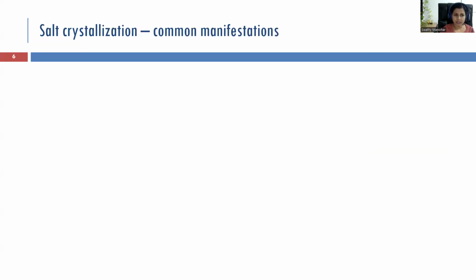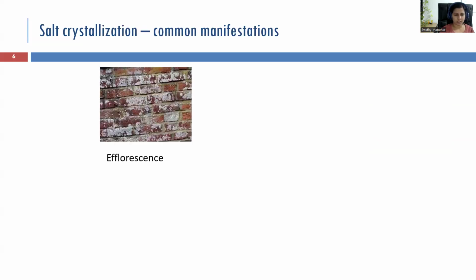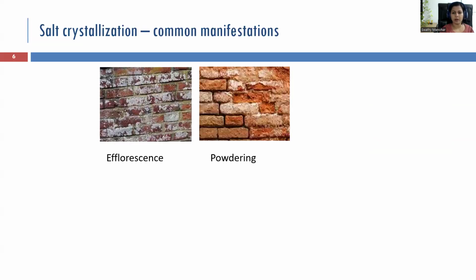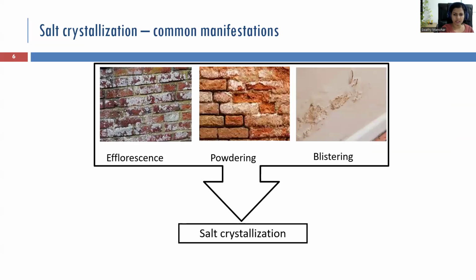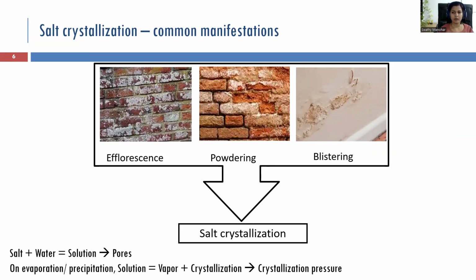What are the common manifestations of salt crystallization? Efflorescence, the white patches you see, powdering, blistering - all of this is because of salt crystallization, which is salt and water from the atmosphere getting into the pores of the system in the form of salt solution. What happens on evaporation? They slowly come out, the vapor will escape out and salt will precipitate on the surface, which is efflorescence or the white patches you see.